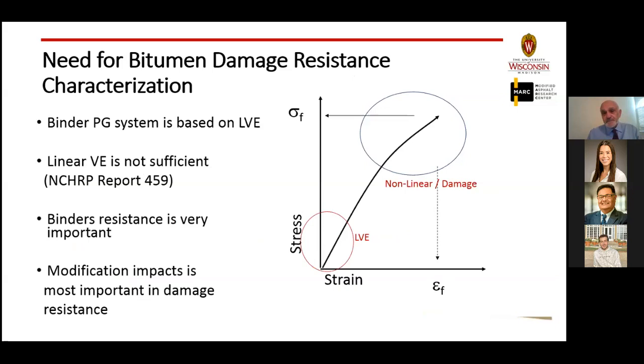So why do we need to look at the damage resistance of binders? I think most of you recognize that if we take a typical graph of stress versus strain, the linear viscoelastic range is extremely small compared to the larger scale where actually failures are happening. Some of us like to call this linear viscoelastic and this nonlinear, but what we see in this circle here is the real damage. This is where the rutting happens. This is where the cracking actually happens.